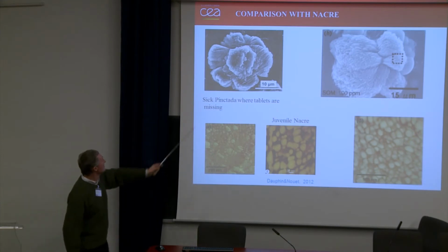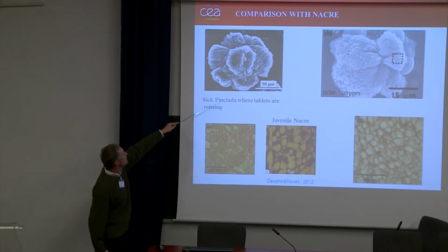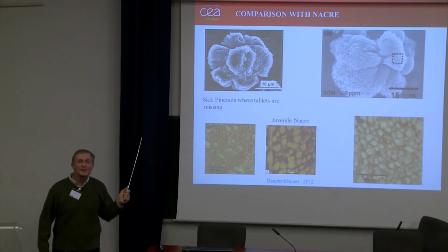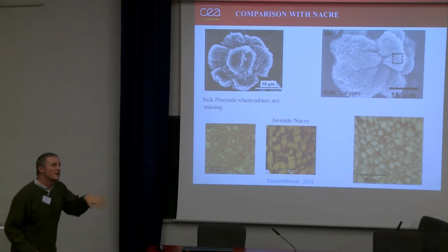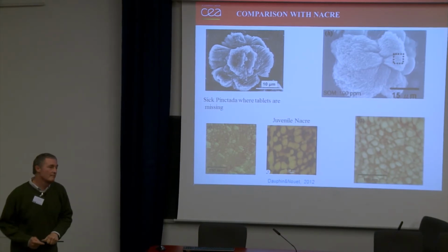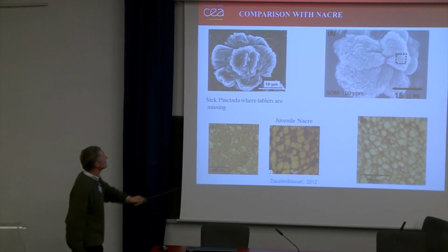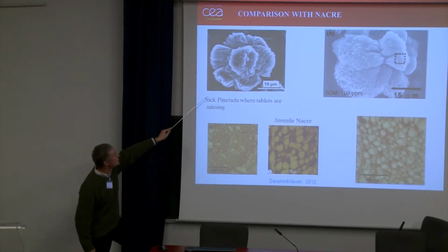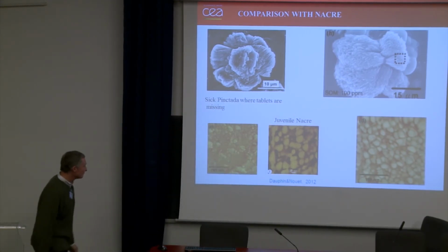And what's interesting is there were also pictures taken from sick Pinctadas. Pinctadas could get some diseases, where this disease was known to damage the insoluble organic part of the organic matrix. And actually, they got this curious shape, which is not so far from this one.